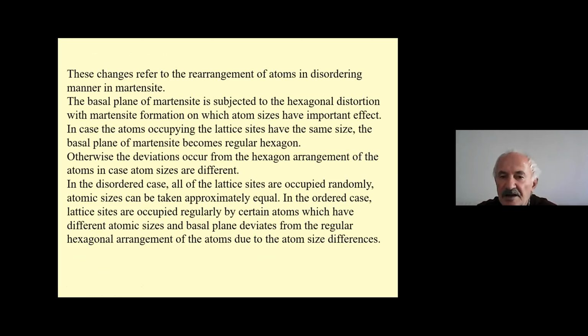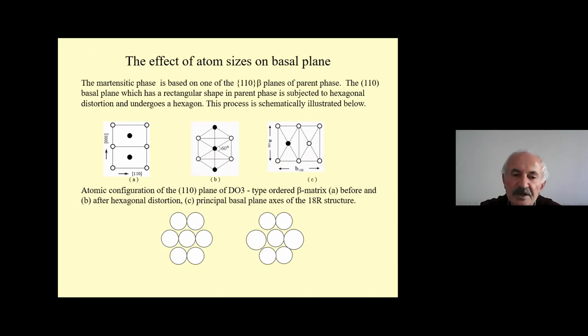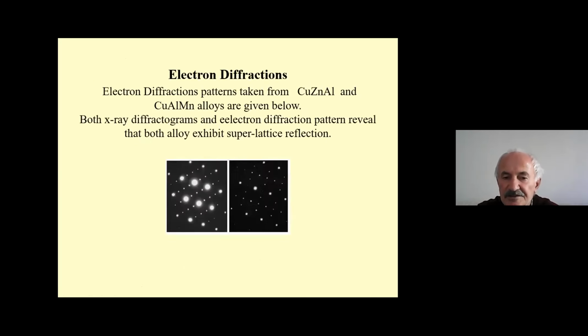Also, this change refers to the rearrangement of atoms in a disordered manner. This is the basal plane of the martensite, which has a rectangular shape, and with the martensitic transformation, the rectangular shape of the basal plane turned into a hexagonal shape. It is important that in the disordered case, we can take atom sizes approximately equal to each other, and this hexagon becomes a normal hexagon. In the ordered case, lattice distribution is regular and neighbor atom sizes are different, and a deviation occurs from the normal hexagonal structure.